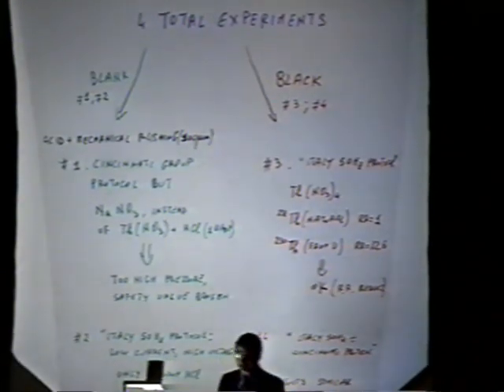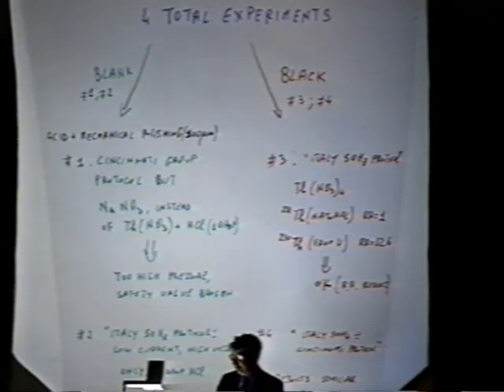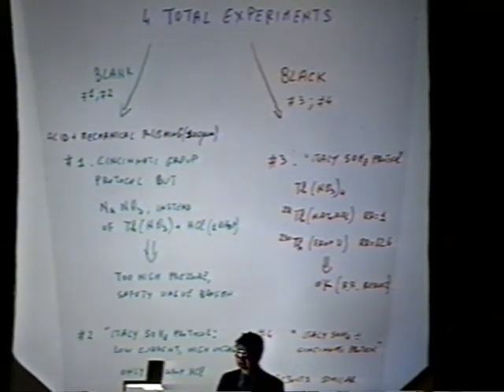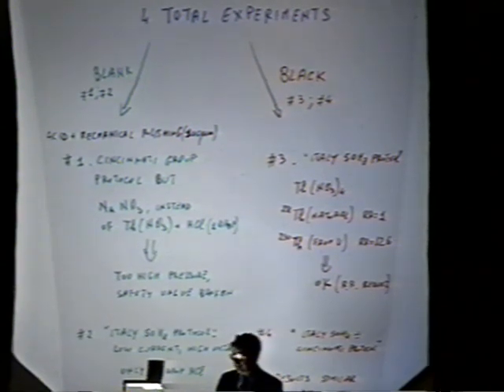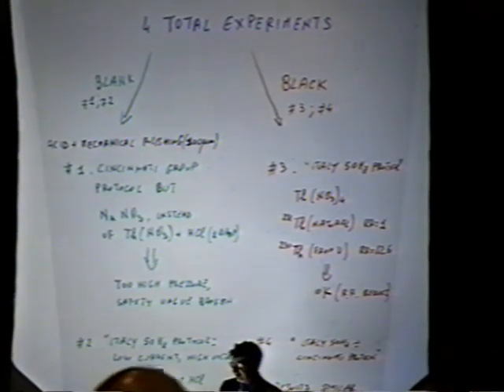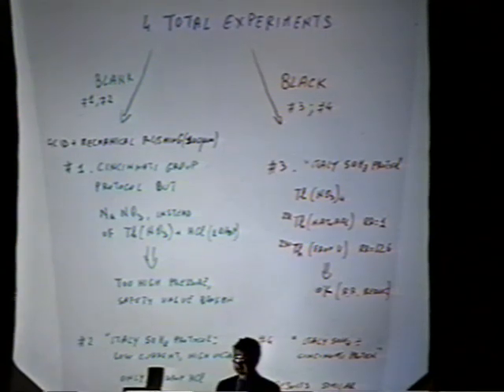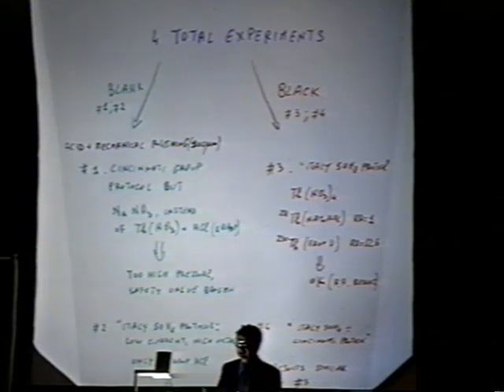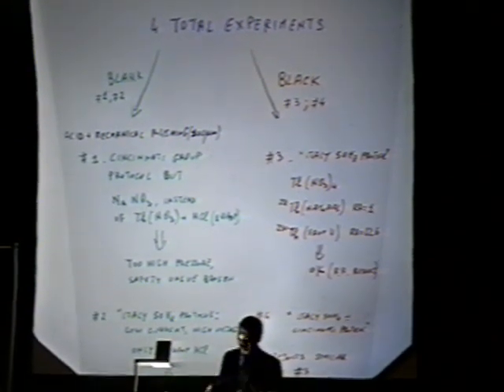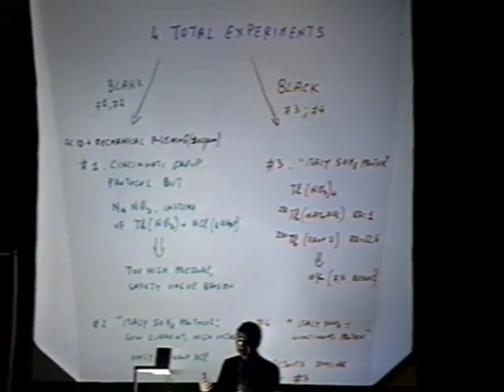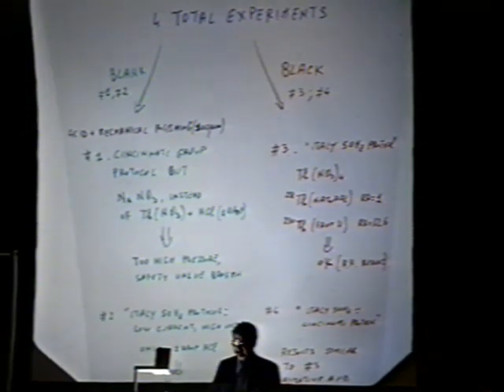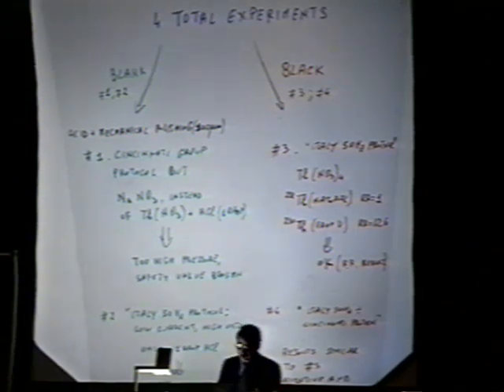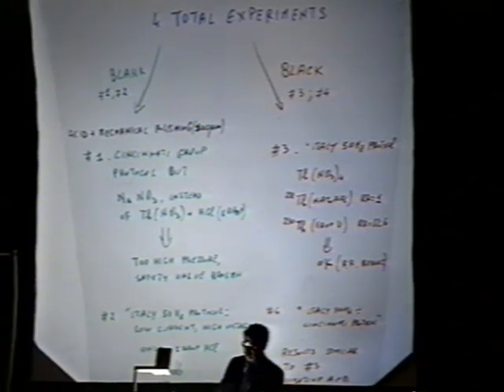We made a total of 4 experiments, 2 blank experiments and 2 thorium experiments. The blank experiment was made mainly to understand how the system works. Before starting the experiment, I asked that the cells be mechanically cleaned. There was the possibility of some contamination from acid etching and so on. Anyway, we tested and found no strange material on the surface, except thorium, zirconium and acid.